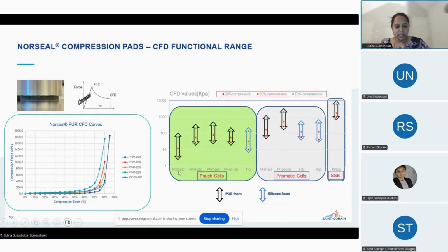For example, take one of the products called PF27200. That's the lowest density. Whenever your pressure requirements are much lower, that is the right solution to use. Whether you're applying 20% or 50% or 70% compression, you can see what the pressure range will be. So it doesn't jump up from, for example, 10 to 1,000 or something. So it's within a reasonable range between your beginning to end of life.